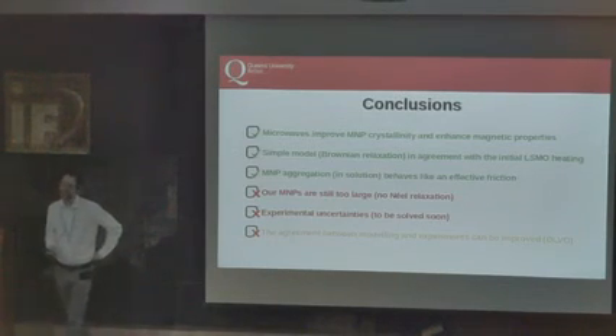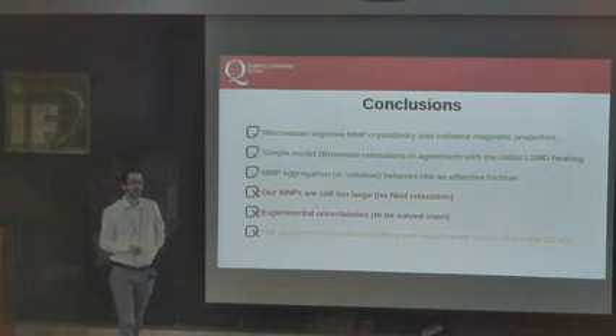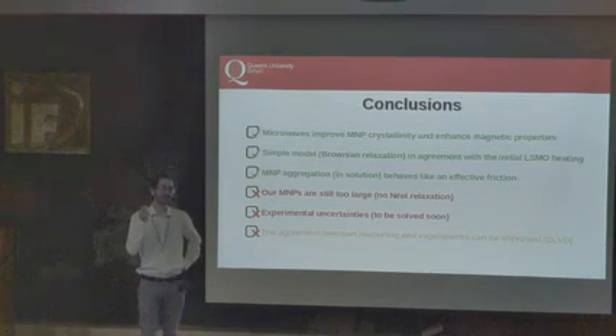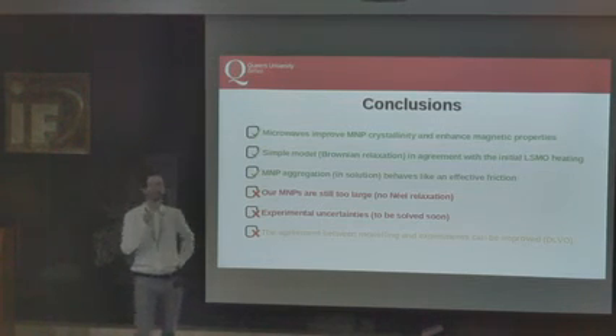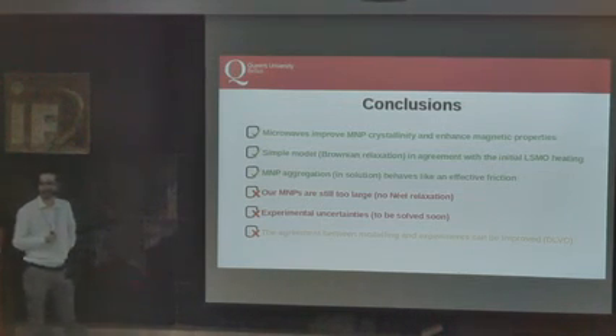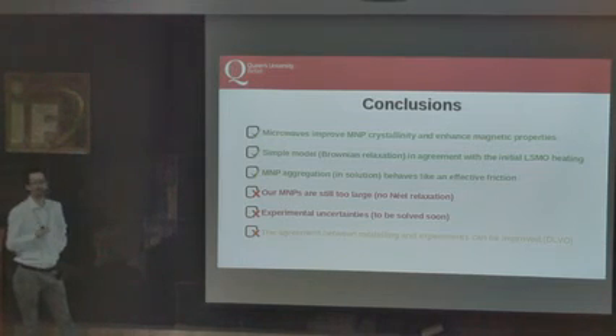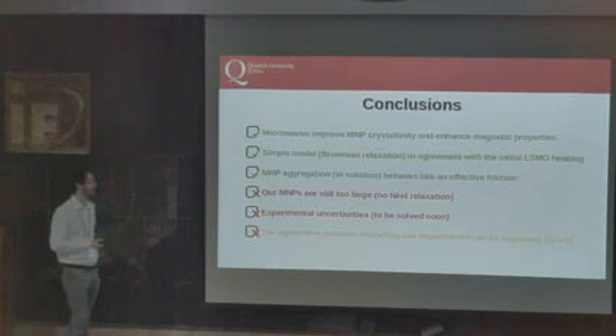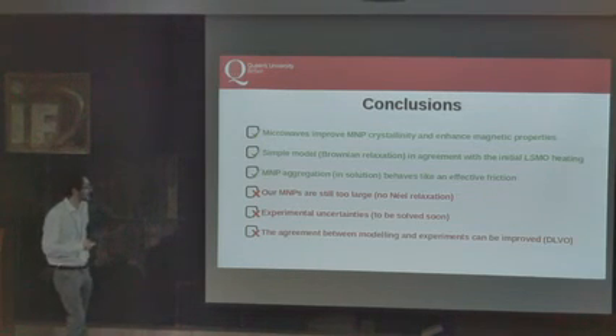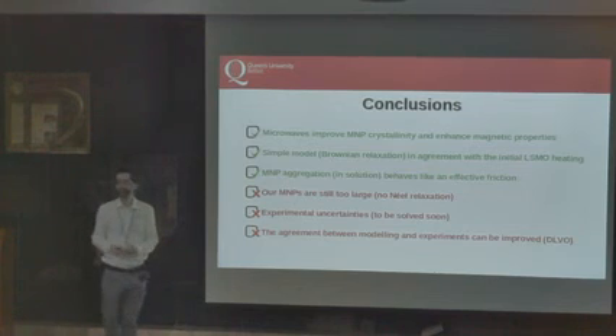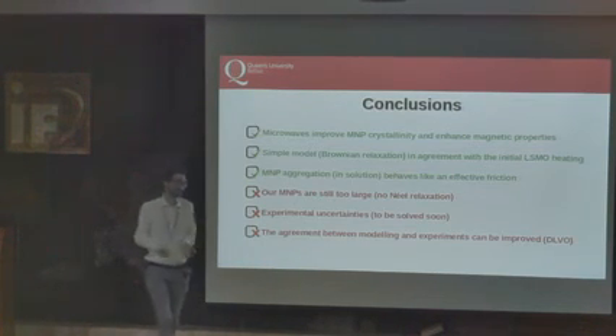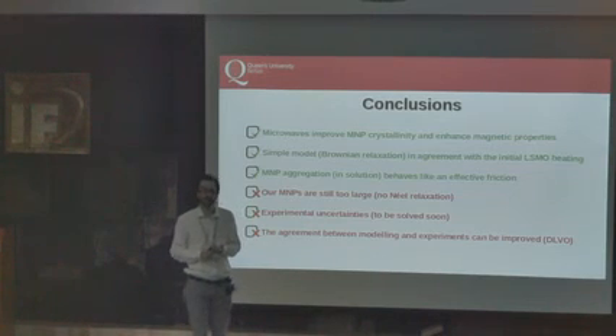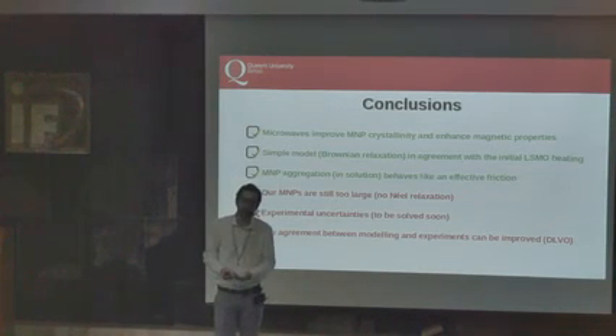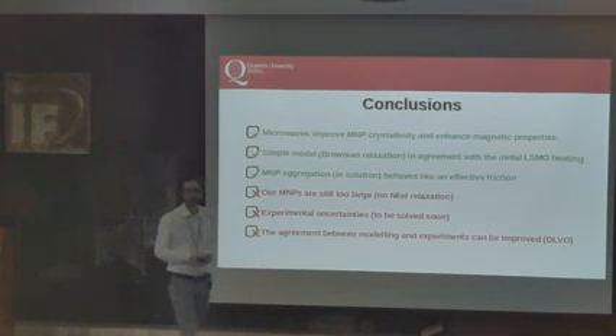There are experimental uncertainties about the quantity measured. In particular, there is no agreement about the protocol to measure the SAR from the experimental curves, especially when you have non-uniform SAR, or if there is a phase transition. And the agreement between the modeling and the experiment can be improved. So from the simulation, it seems that we can rule out the presence of chains, because they decrease too much the SAR. It's not the value observed.